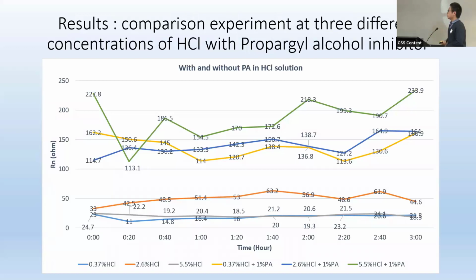So here are the results obtained in HCl solution with and without propargyl alcohol. As you can see, the top 3 are in 3 different concentrations of HCl, but with 1% propargyl alcohol. They got a higher Rn value, which means the propargyl alcohol did provide some protection for the iron samples. And the bottom 3 are just pure HCl solution. The top one, which has the highest Rn value, is the 5.5% HCl solution with 1% propargyl alcohol. It got better protection.